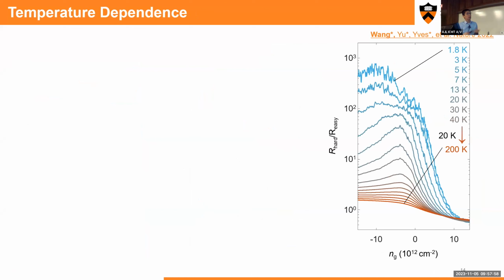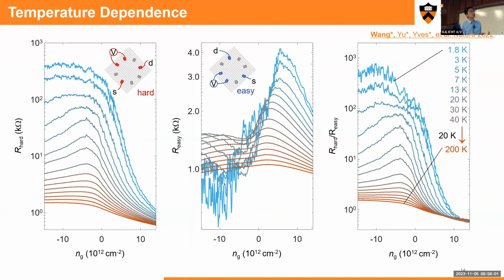And we keep going. We can characterize this anisotropy with temperature dependence, just to confirm that it's not coming from disorder, or from not twisting it in a very good fashion, or from strain on the system. First of all, you can check that the anisotropy ratio decreases with increasing temperature. And the second is that it shows a completely contrasting behavior along the hard direction and easy direction. Along the hard direction, the resistance shoots up with decreasing temperature. But along the easy direction, the resistance goes up and then comes back down like a metal at low temperature.